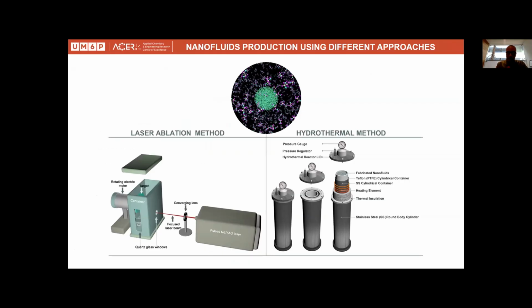There are different ways of making nanofluids in general. Either you use laser-based methods or hydrothermal methods. With a laser-based method, you have a source of laser and a target, and you can do ablation in liquids, which means you can introduce nanoparticles directly inside the base fluid or the heat transfer fluid. Otherwise, you use a hydrothermal method. We compared these two methods and found that laser ablation is much better because it allows us to produce nanoparticles even below 10 nanometers. Below 10 nanometers, the nanoparticles are charged and have the property of electrostatic stability, which means we don't really need to add surfactants and other materials to stabilize the nanofluid.